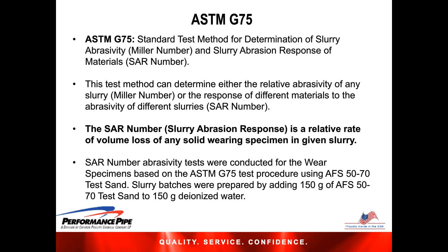The slurry abrasion response number, or the SAR number, is a relative rate of volume loss of any solid wearing specimen in a given slurry. In our particular case, which is a fairly standard test protocol for this test, the test was conducted using AFS 50-70 test sand, and basically 150 grams of sand and 150 grams of deionized water, meaning that the concentration was 50% by weight of the abrasive media, which was in this case, again, sand.